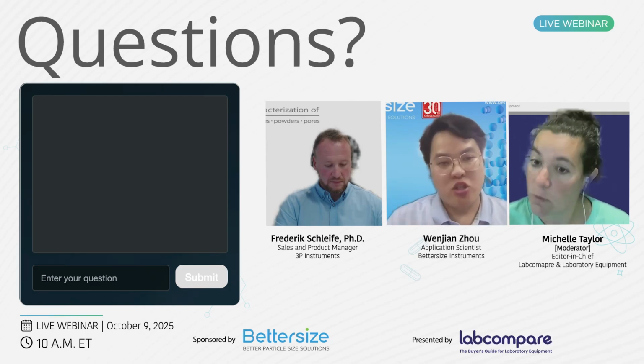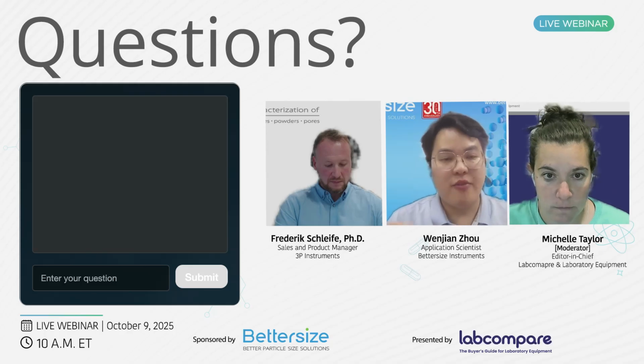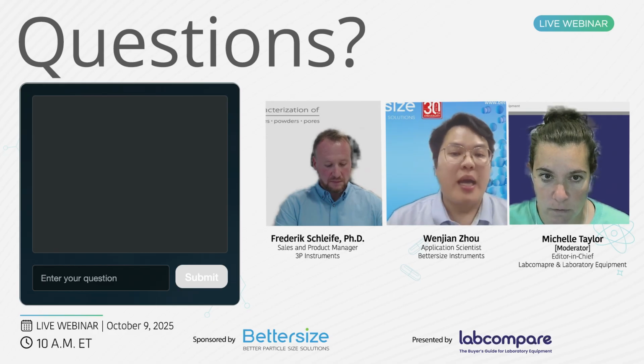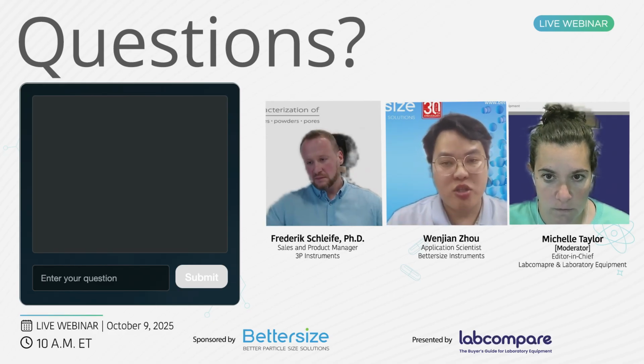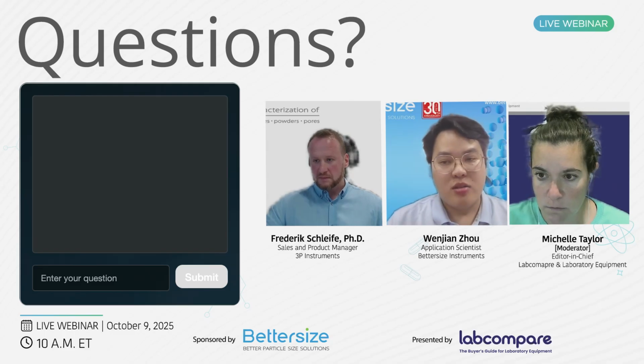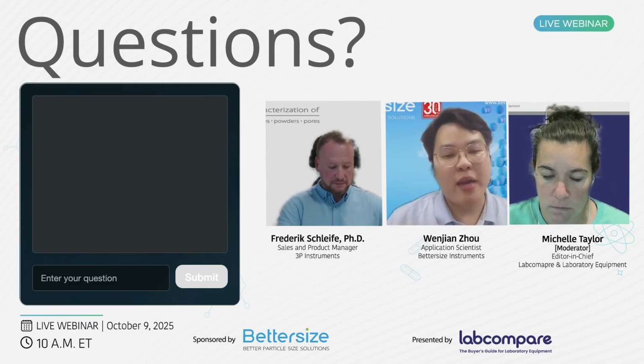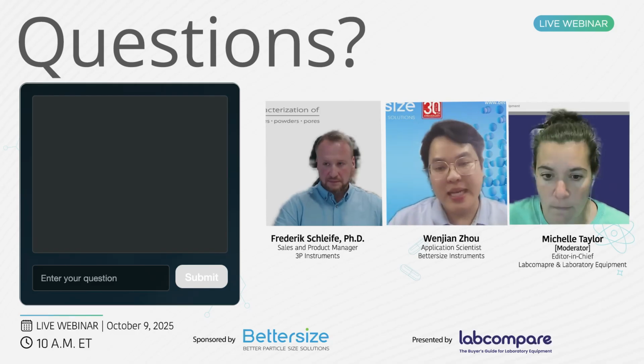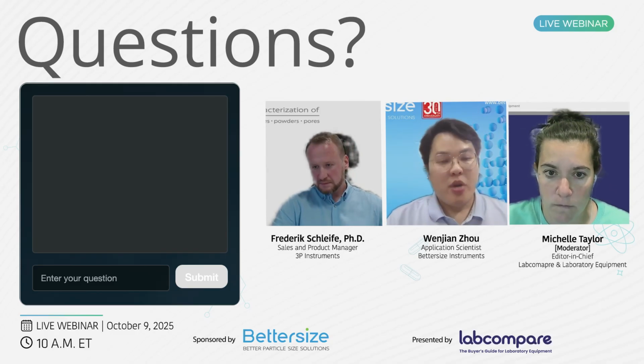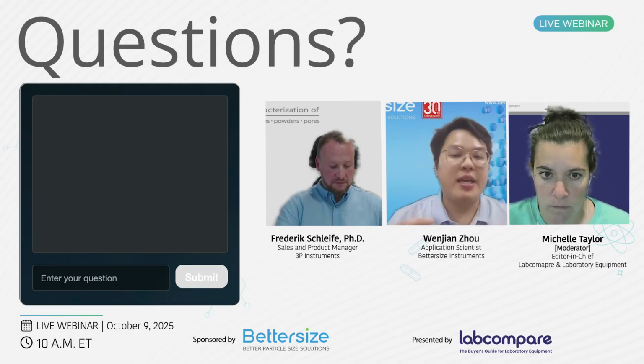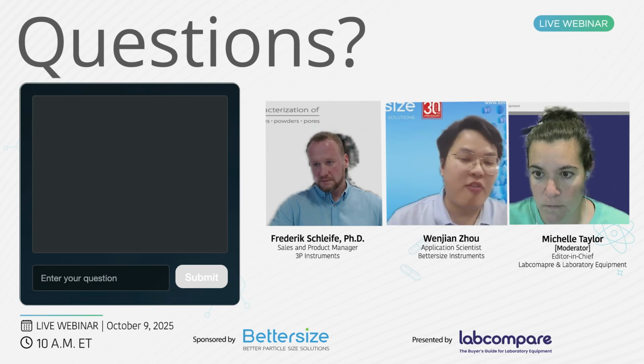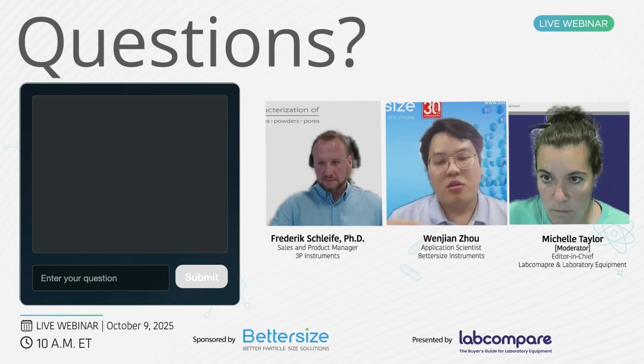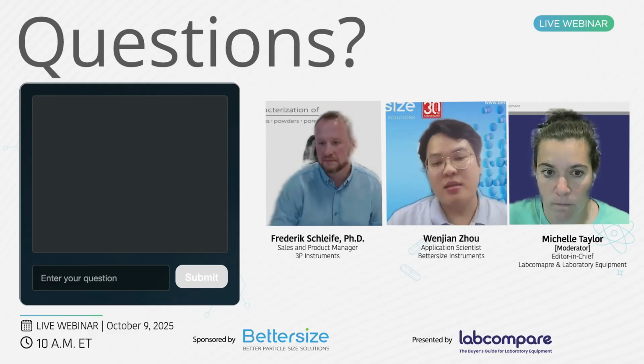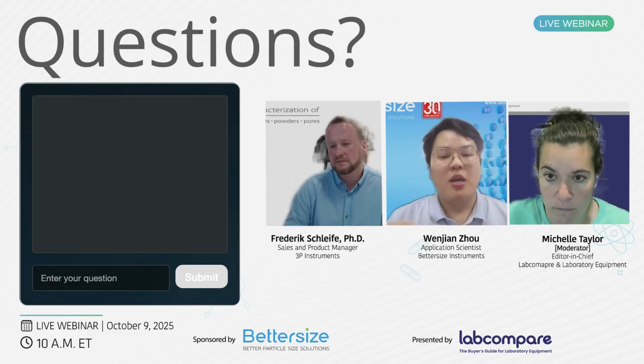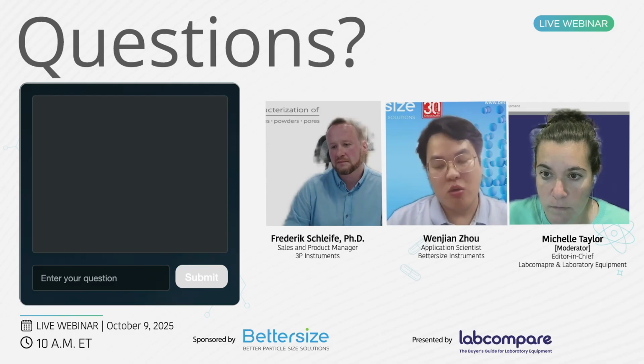Absolutely, you can measure with only image analysis. If you focus on particle shape analysis, you can just use image analysis. But there is a problem, and that is we cannot use a camera to capture submicron particles. That is why we need laser diffraction, and laser diffraction applies Mie theory, which is designed for measuring tiny particles. So in general, we can combine these two techniques: the laser diffraction for the small particles, to ensure high measurement accuracy, and the image analysis for the coarse particles, to make sure that we won't overlook the coarse particles in the samples.